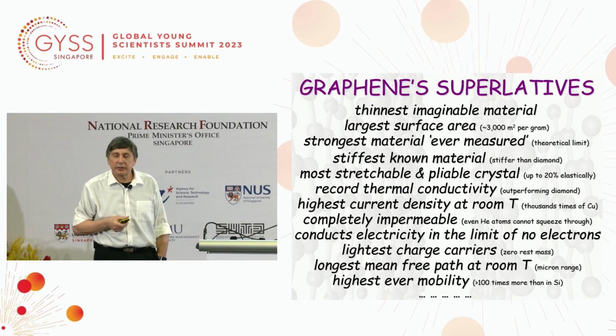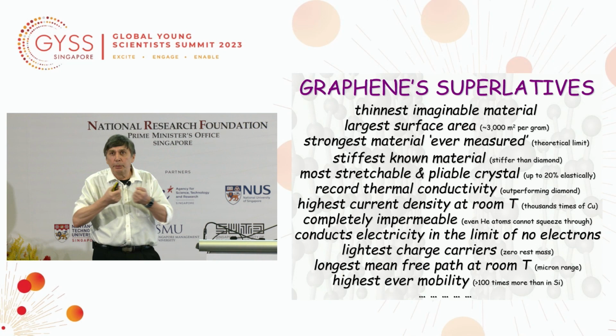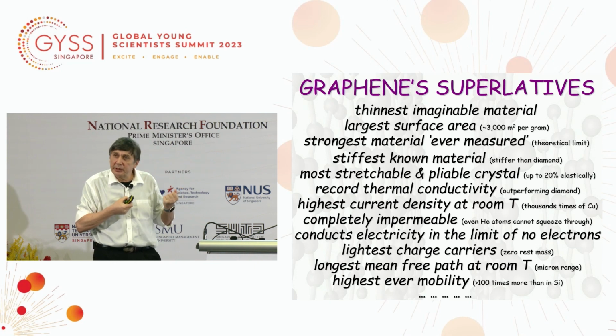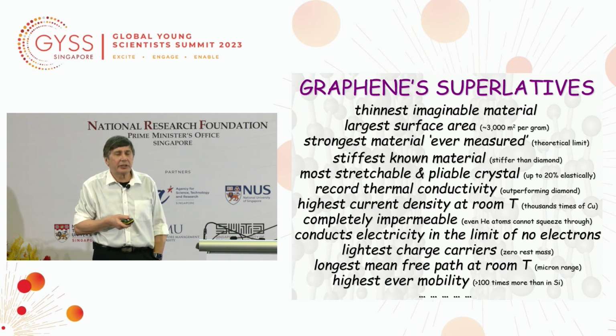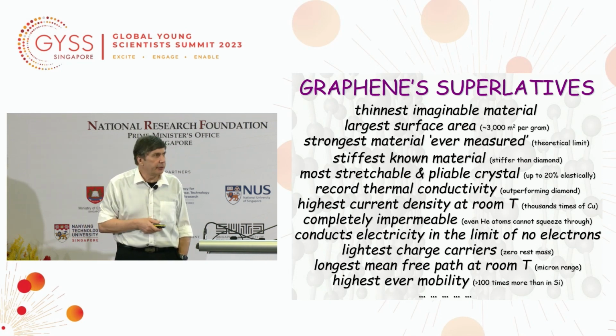but that is kind of expected from the thickness of the material. What we didn't expect is that it turned out to be the strongest material, at least in the lab, ever measured. It's not only strong, it's stiffer than diamond, but try to pull or compress diamond, you wouldn't do anything. You would not be able to, but this material is pliable, is stretchable, this graphene, very unusual properties. It also shows record thermal conductivity, outperforming diamond, and it carries current 1,000 times higher per thickness than copper or gold or silver can. And there are plenty of other properties.